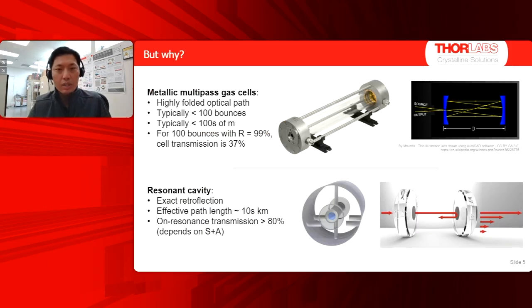So then why pursue these high reflectivities at all? Here's a couple of examples, by no means exhaustive. But if you consider multipass gas cells that are often made with metallic mirrors, you have an analyte that's not very highly absorbing, and so you just want a very long interaction path. And so these multipass cells give you a highly folded optical path, sometimes with hundreds of bounces and up to hundreds of meters of interaction length. But if you think about it, for 100 bounces with reflectivity of 99%, the transmission through this cell after all those bounces is only 37%. And obviously, if you have lower reflectivity, this is a strong function of reflectivity. And so that cell transmission is going to drop rapidly as a function of reflectivity.